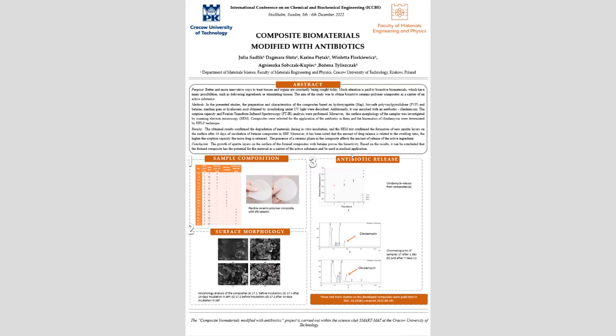We can move to the antibiotic release, and on the first diagram, we can see the percent of clindamycin released, and after 7 days of immersion, the clindamycin content reached 55% for sample 17. It's a sample with betaine. And the next two diagrams are chromatograms and show the retention time of clindamycin, which is 4 minutes and 41 seconds. And what's the conclusion?